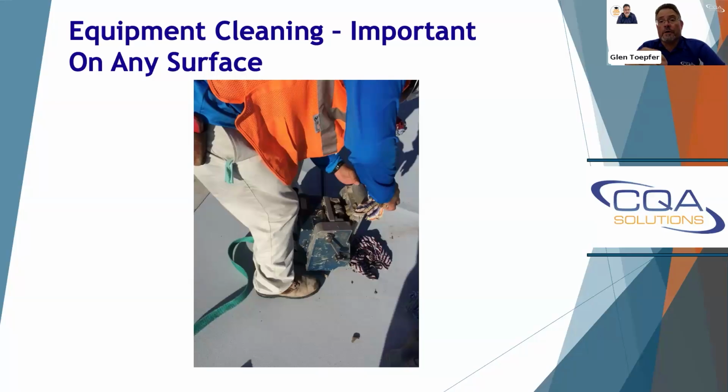And so you get all that pressure going through that intersection. You're so thick there, almost 200 mils or whatever the number was earlier, just for your two sheets of overlap if it's textured, but then you throw in a third or a fourth sheet there. That's a lot of pressure, and you're trying to have that machine go through and maintain that pressure. Something's got to give. And unfortunately, a lot of times, the equipment, I think, does loosen up over time, and it results in failures that could have been avoided, particularly when you're dealing with the textured interfaces.